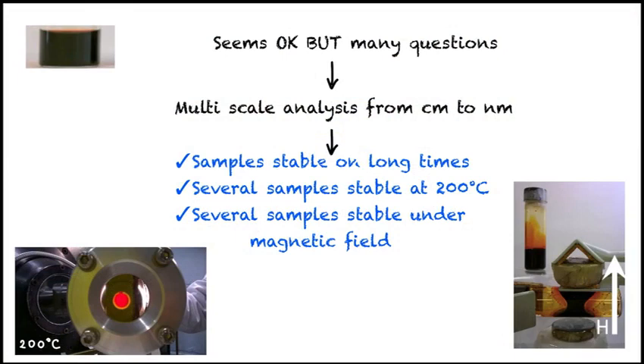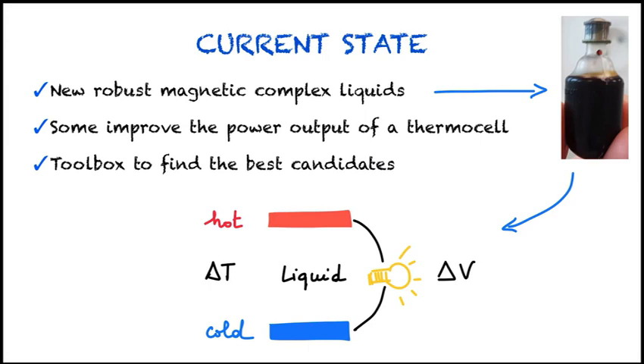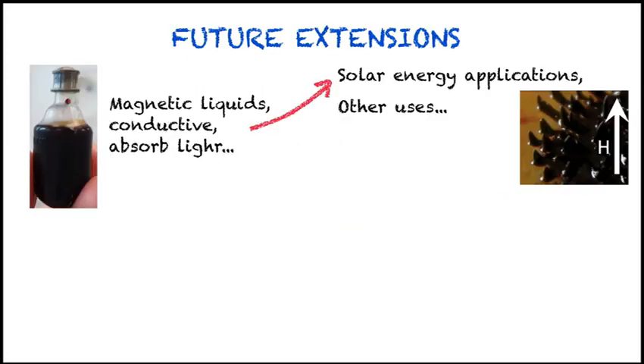Thanks to a multi-scale analysis from the centimeter scale by eye to the nanometer scale by several techniques, we could demonstrate that samples stable on long times are obtained, several samples are stable at 200 degrees, several samples are stable under a magnetic field. At this stage, we thus have robust magnetic complex liquids. Among these liquids, some improve the power output of a thermocell, which is measured by other partners. We also have a toolbox of techniques and processes to find the best candidates and develop this family of liquid nanomaterials. This also opens future extensions.